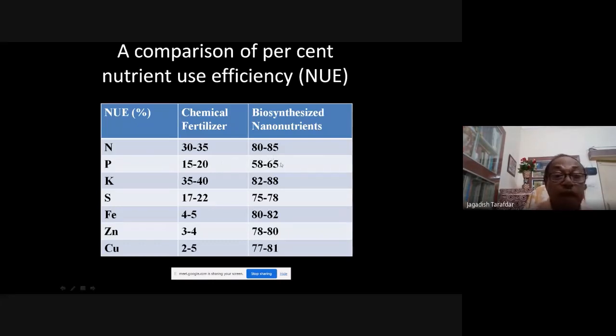At least we are getting 60% on an average use efficiency. Potassium from 35% to 88% use efficiency. Sulfur again 4 times improvement in use efficiency. And interestingly, for all micronutrient chemical fertilizers, the use efficiency is not more than 5%. Not more than 5% for any micronutrient. So that use efficiency we can increase 20 times. I mean, when we are using nanoparticles as micronutrient, we are getting at least 82% use efficiency. So that way you can save your fertilizer resource a lot.